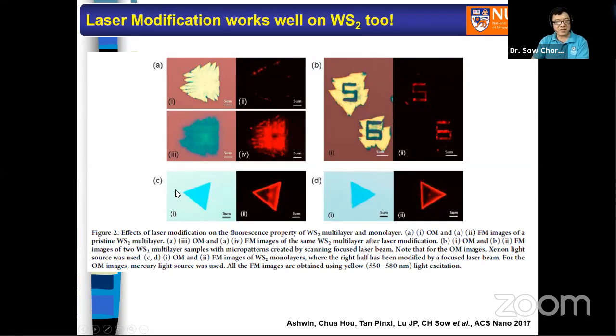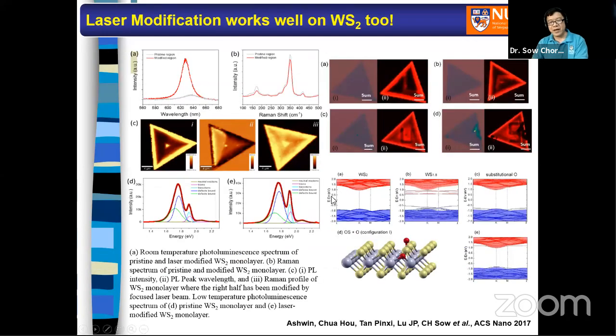You see this monolayer WS2, they use a laser beam with very careful laser power control, only modifying the right-hand side. Can you see that the right-hand side becomes much brighter in terms of fluorescence compared to the left? The story behind is, again, local modifications with oxygen playing a big role. Oxygen sometimes is bad, sometimes it's good. So you have to find the systematic window of when it's good. Then we characterize them with the help of DFT and understand the physics behind.